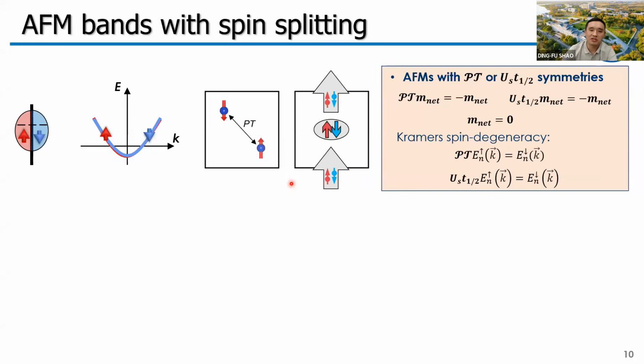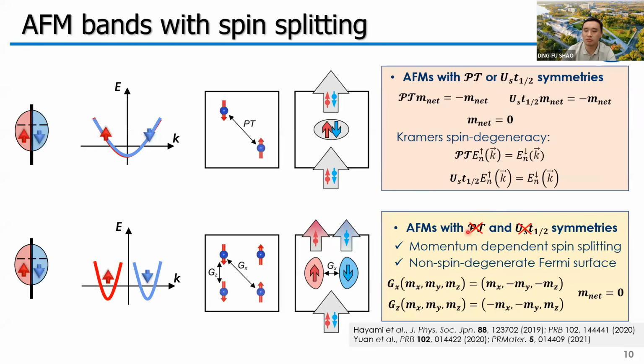But previously, by default, people considered that antiferromagnets can only have a spin degenerate band structure. That is because antiferromagnets usually have some symmetry operations such as inversion plus time reversal, where without spin-orbit coupling, we can have spin rotation plus translation. These symmetry operations enforce zero net magnetization and also enforce the Kramers spin degeneracy everywhere. So obviously, if we can break these two symmetry operations, we can have a non-spin degenerate band structure.